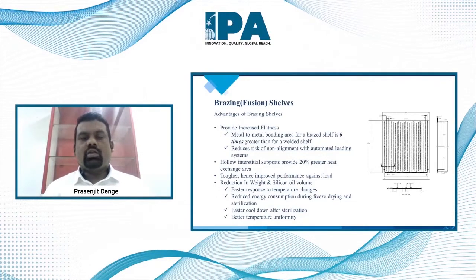And since it's hollow, we are getting 20% greater heat exchange area, because in case of the solid, there is no flow of the silicon oil through the solid baffles. As I said, it's tougher, so there is improved performance against the load, for sure. And of course, there is a reduction of the weight of the shelves, because these shelves can be slightly